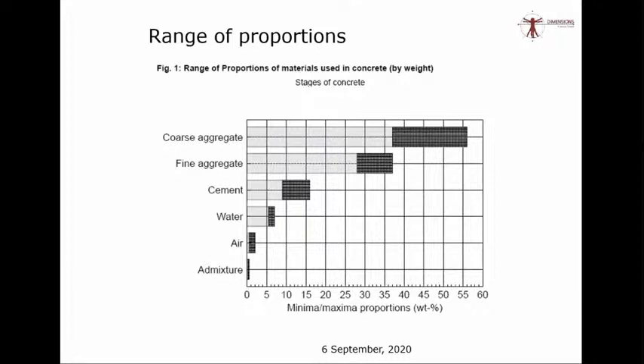But what we should understand from this picture is that coarse aggregate constitutes the maximum volume of the ingredients, then comes the fine aggregate. When you compare the volume of coarse aggregate and fine aggregate, cement is somewhere in the range of 10% or so when you put both together. Then water to cement is always in the range of 0.5, 0.55. Almost 50% of water would be required based on the quantity of cement you use. You should also appreciate that there is some air content. You cannot make a zero air content concrete. At least till now nobody has produced it, and you have various degrees of admixtures, but their influence on the rheology is going to be great.